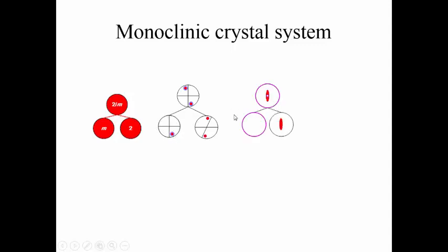So when we do our symbols, here's the mirror in the plane, and that's translated up here to the mirror in the plane, and here's the twofold. The twofold, we've had that before, and now when we do the 2 over m, we're going to generate this inversion point here, and we indicate it by that little dot over there. And now we can see the generators a little more clearly. We can specifically set this up as 2y, the generator for 2, and the generator for m, and then if we combine those, we can use these 2 generators to generate the 2 over m.